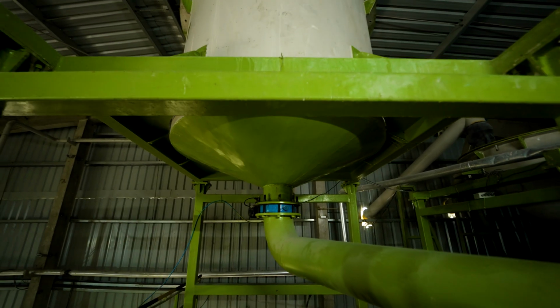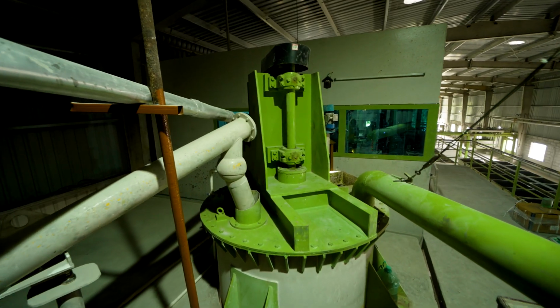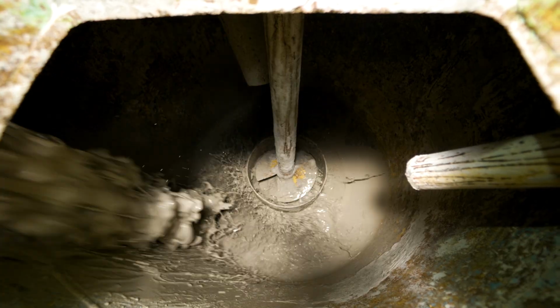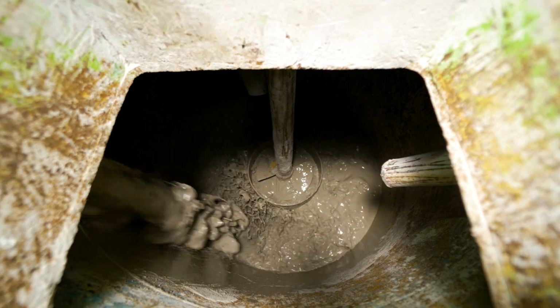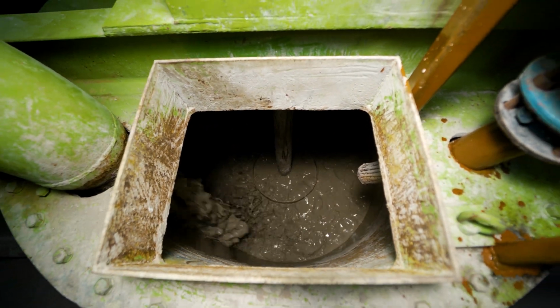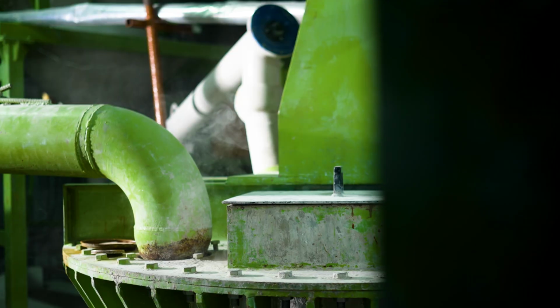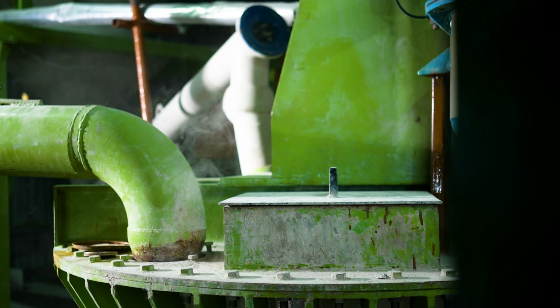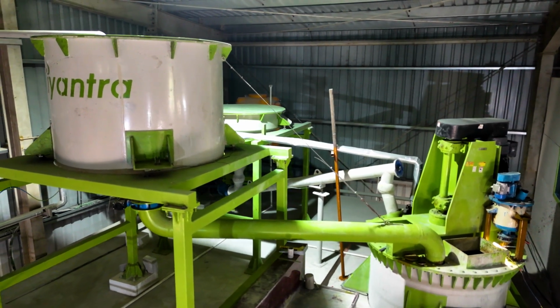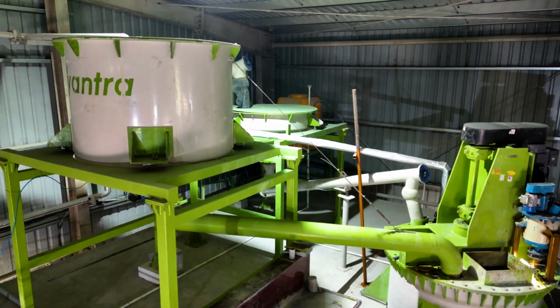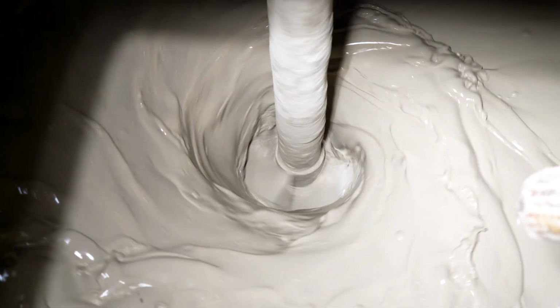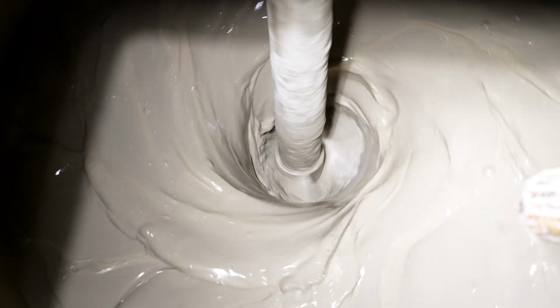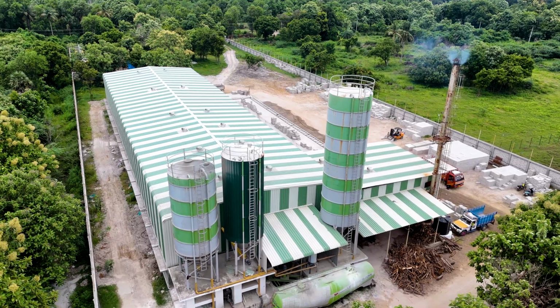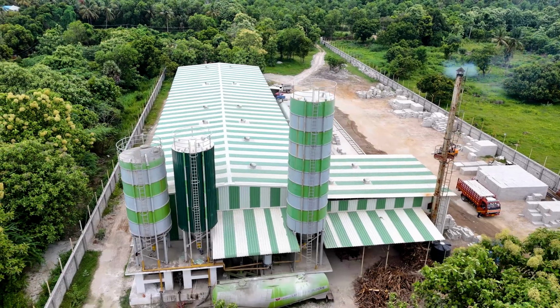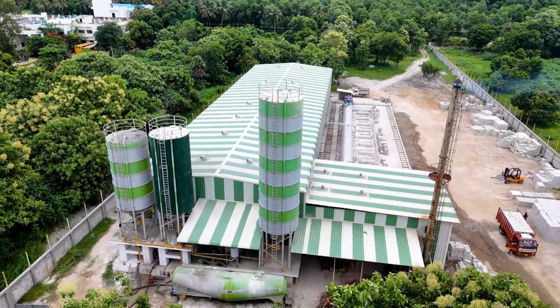Foaming reaction. Aluminum powder, 0.05% to 0.08% by weight, is added last. It reacts with the lime in the slurry, releasing hydrogen gas. This reaction forms millions of tiny air bubbles, causing the slurry to expand and create a lightweight structure. Resting time. The mixed slurry is allowed to rest for a few minutes to ensure proper aeration and consistency.